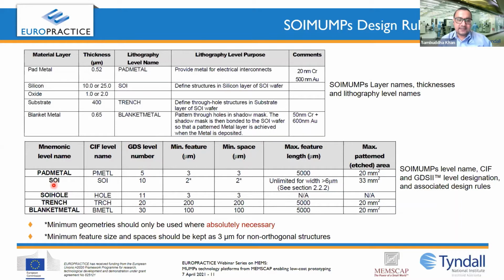For example, for the SOI layer, the minimum feature is 2 micron, and the minimum space is also 2 micron. That means you cannot get anything below 2 micron space and feature both. But for 2 micron and 2 micron, there is a star here. It says that minimum geometry should only be used when absolutely necessary, and if the geometries are orthogonal in nature. If they are non-orthogonal structures, then you should keep 3 micron as the minimum feature and minimum space. And then there is something called the maximum pattern area. I'm coming to my next slide, where that is defined.